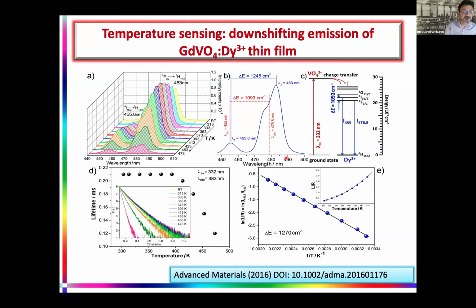And as you can see on this diagram, when we plot in this so-called Arrhenius type plot, since it's a Boltzmann distribution, this ratio falls on a straight line, which means that we have successful calibration. On the left side, you can see lifetime measurements. Lifetime is also, in addition to intensity ratio measurements, one of the mostly used tools to determine temperature from luminescence. However, with lanthanides, there is a wide range of temperature where the lifetime of excited states does not change with temperature, so only at high temperature can it be successfully used.